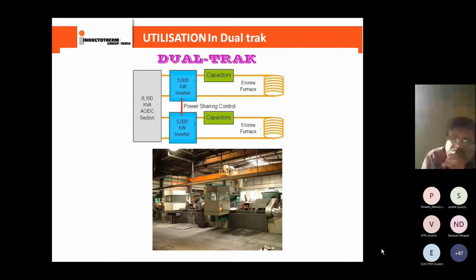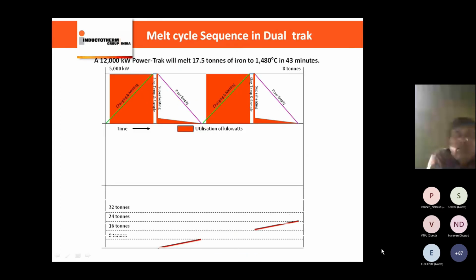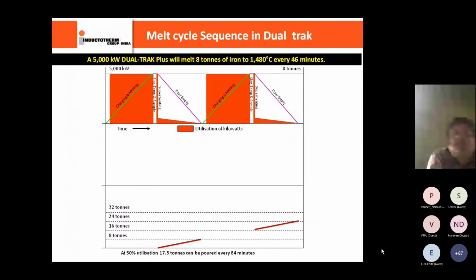improve the utilization, we have the option of dual tracks. Wherever you are melting and pouring in one shot into ladles, generally dual tracks are not required. But in some foundries where liquid metal is required to be supplied continuously to machine molding or high pressure molding lines, dual tracks and tri tracks are essential. The purpose of dual track or tri track is that when one furnace is on holding, pouring, chemistry adjustment, or deslagging, the entire power can be pumped into the second furnace where the actual melting takes place, and vice versa. So with almost the same kilowatt per kg combination, we can improve productivity by almost 20 to 50% within the same kilowatt and kg combinations.